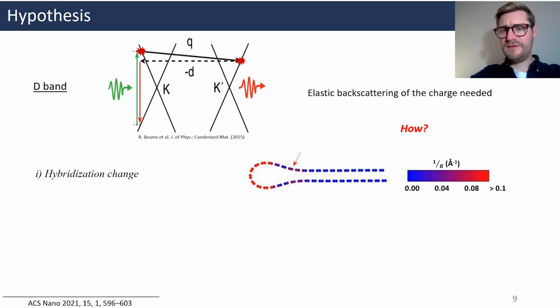The first hypothesis involves the hybridization change near the cavity. It is known that the curvature induces a partial hybridization change. For example, here the red arrow on the scheme shows the presence of a line of partial sp2-sp3 hybridization in between two sp2 zones. This line comes necessarily with an energy barrier able to backscatter a charge.